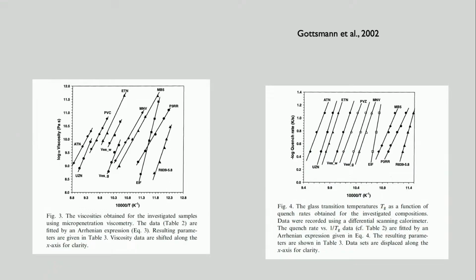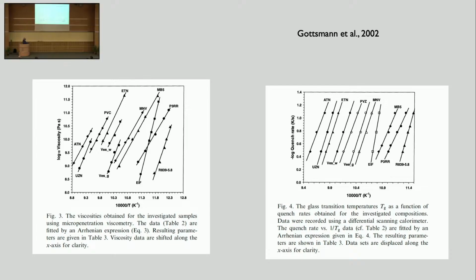And here you can see two kinds of data. They look like the same kind of data. You have to look at the axes, and you see this is the log of the viscosity versus reciprocal temperature. You've already seen that kind of plot. And these are the same samples, but it is the glass transition temperature as a function of quench rate. And the message of the story is that the slopes that you get from this are the same as the slopes that you get from this.